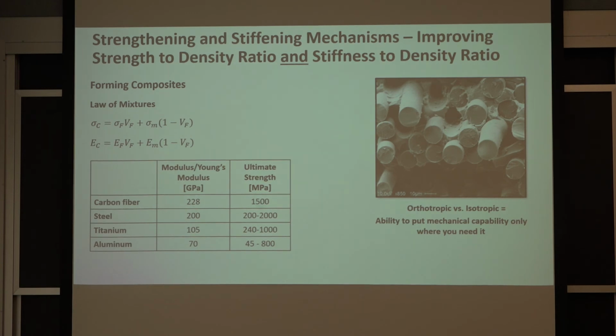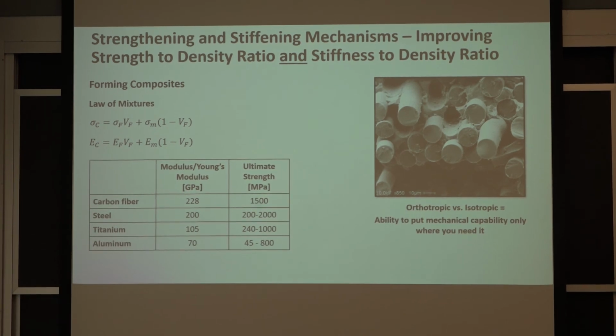So up until now, the 4 different strengthening mechanisms I showed you were all about changing the strength to density ratio. There are some exceptions, but 30,000 foot view, this is really the only way to increase the stiffness per density ratio. Like I said, there are exceptions. For example, aluminum lithium, I believe you change the modulus a little bit and also decrease the density when you put in like 6-8% lithium in aluminum. There are airplanes out there, especially in the military, that use this aluminum lithium alloy.